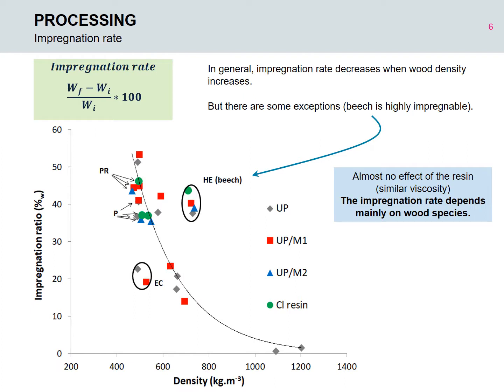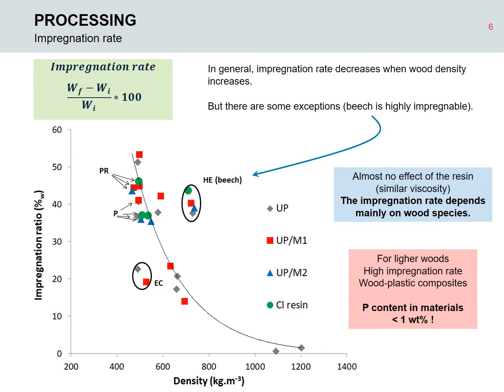There is almost no effect of the resin because all the resins have a similar viscosity, and so we can conclude that the impregnation ratio depends mainly on wood species. Note that the impregnation ratio reaches 50% in some cases. It's very high, and we can consider our materials like wood plastic composites. But in all cases, the phosphorus content does not exceed 1%. It is quite low.